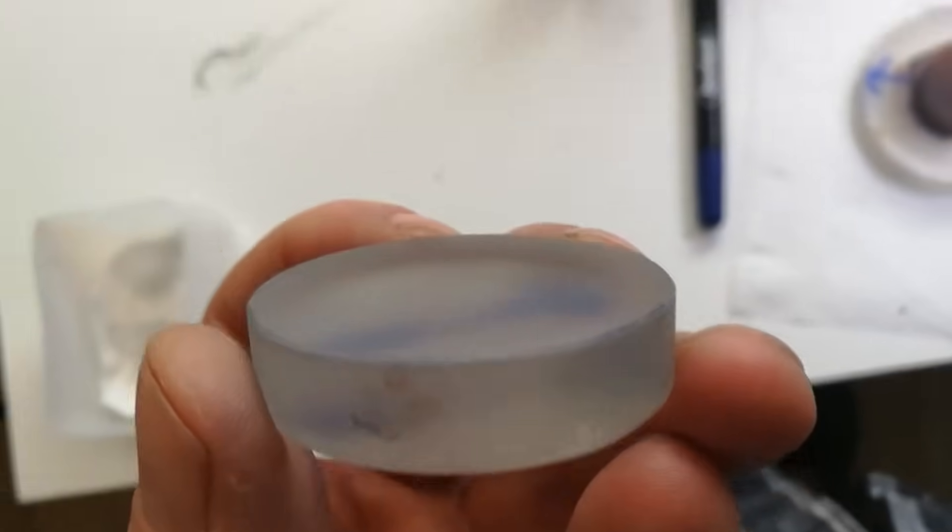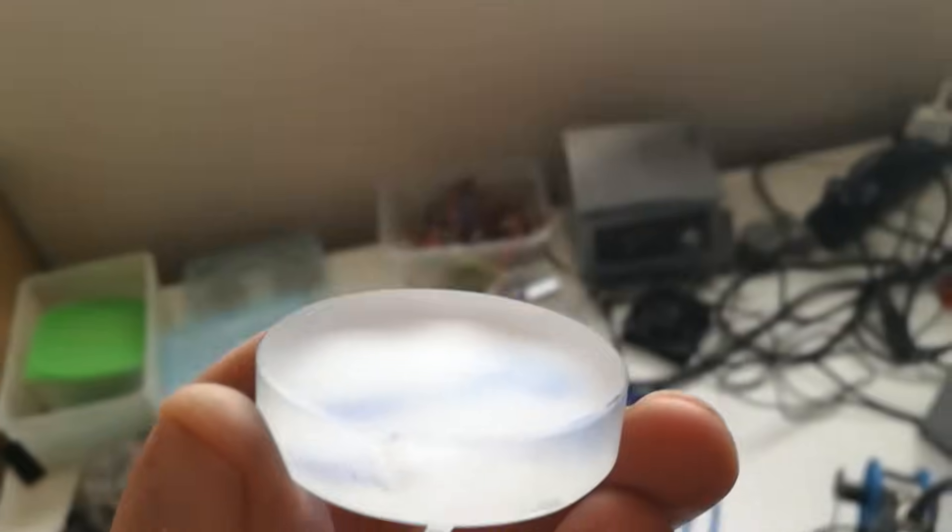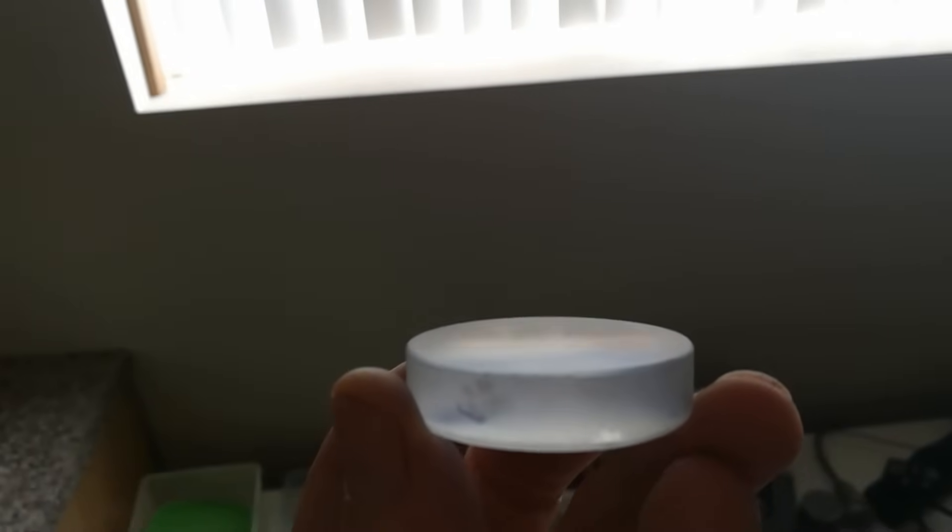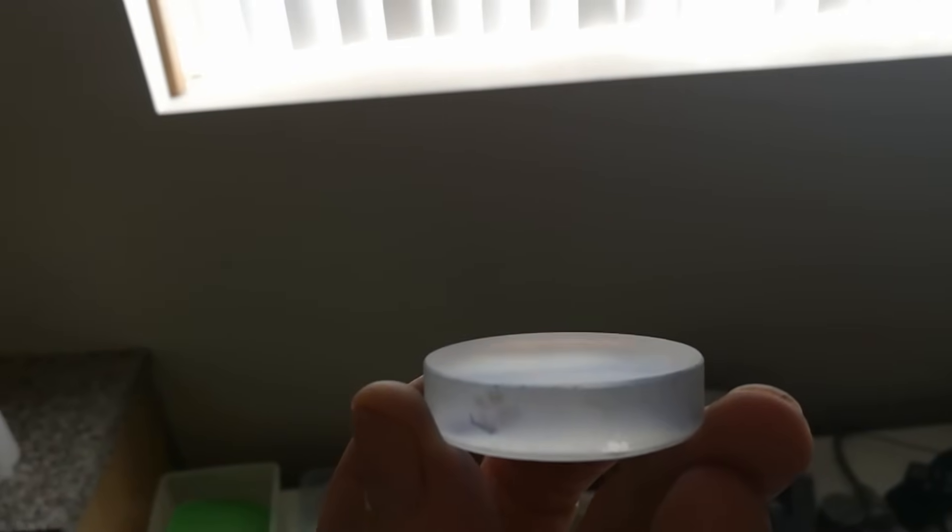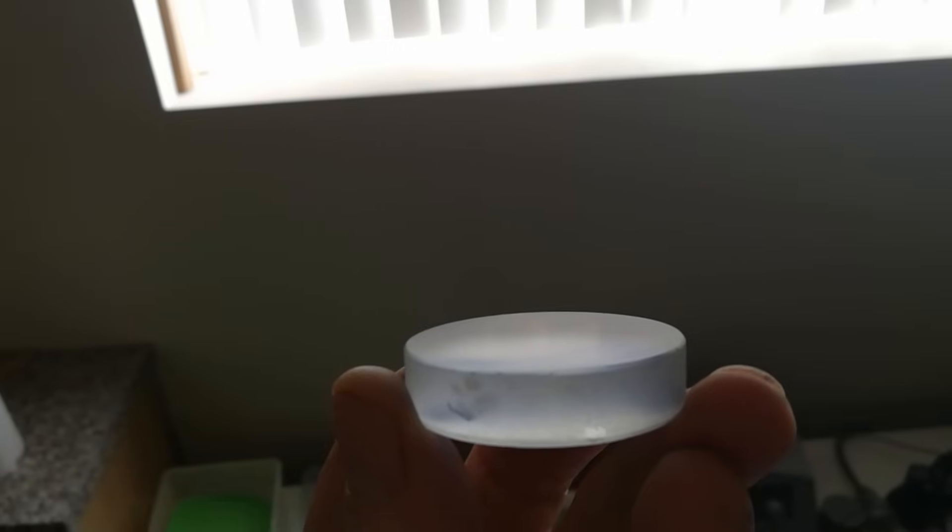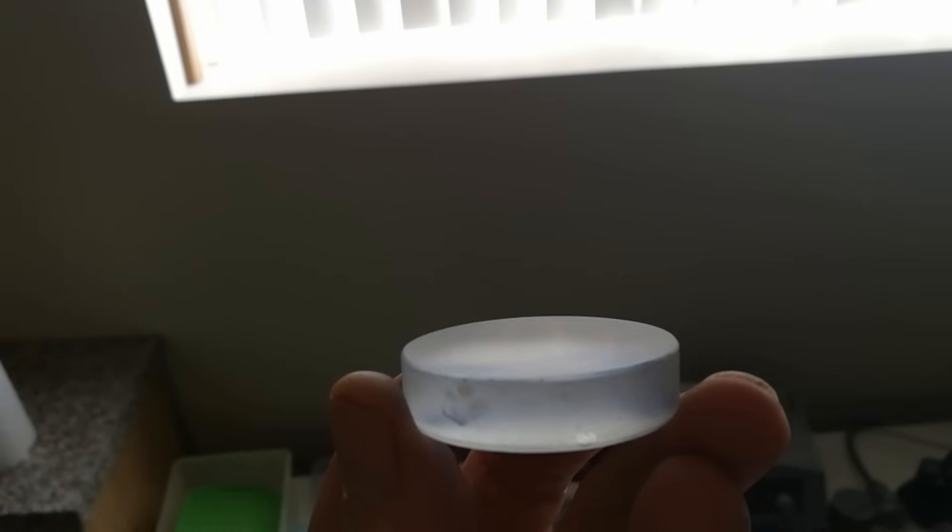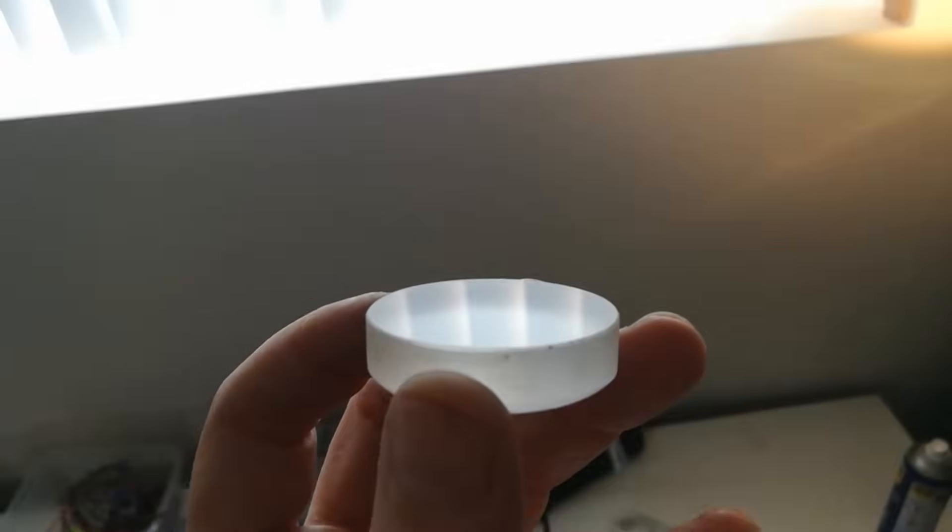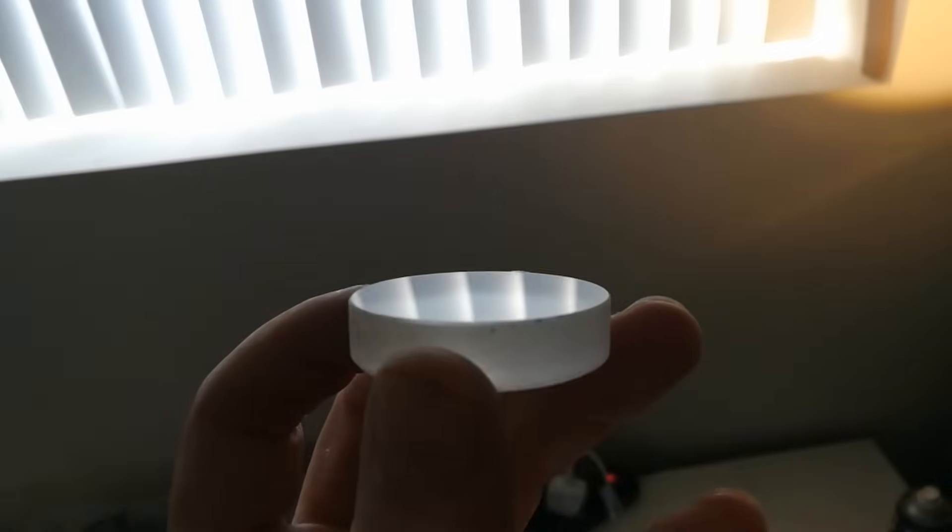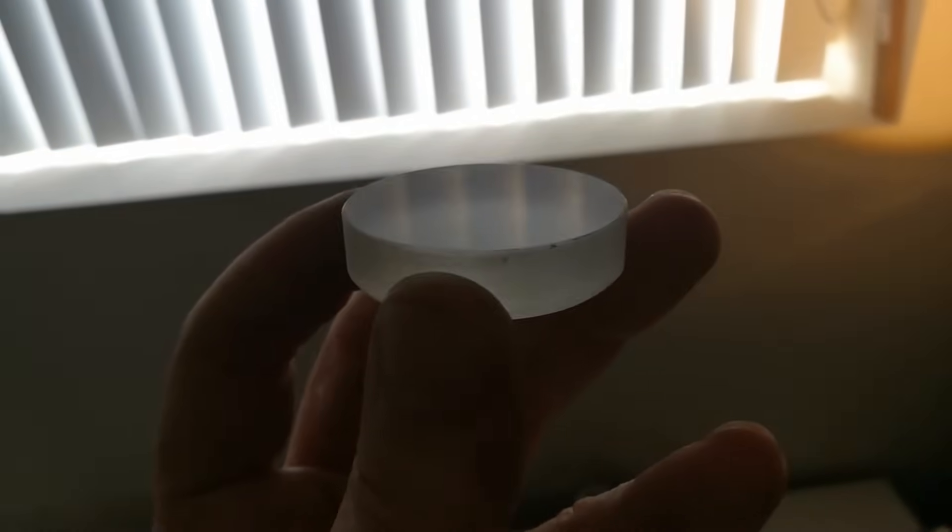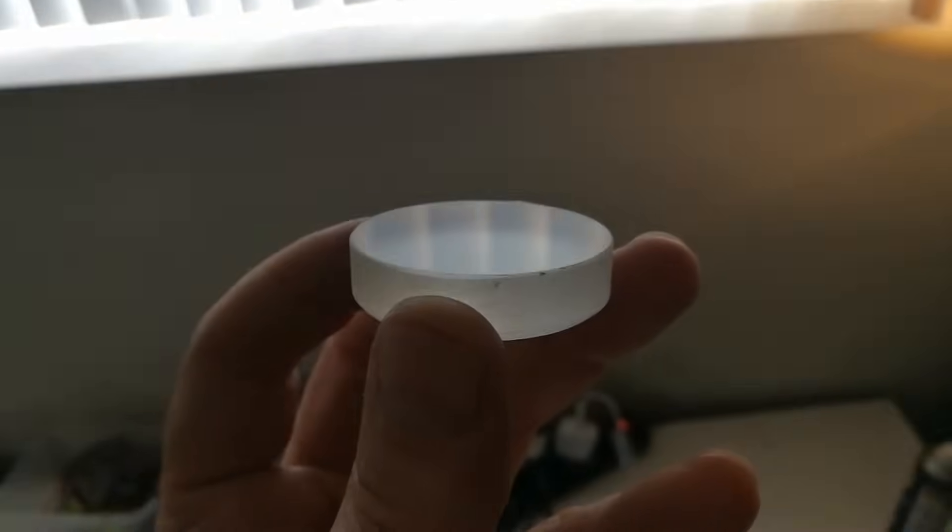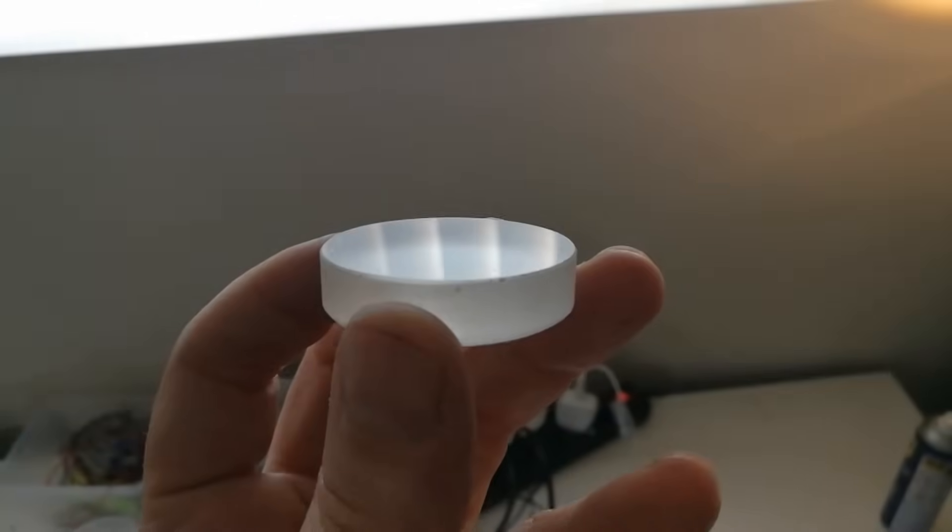As we get to smaller particles, the surface gets more and more shiny when examined under a small viewing angle. When we get to the last grain, let's say 1200 mesh, we should be able to observe surface reflections under an angle of almost 20 degrees.